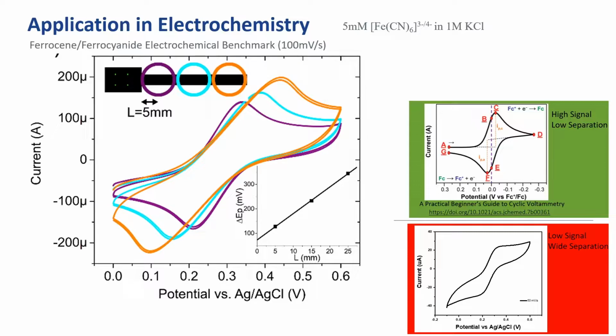To investigate the trade-off between area consumed by the plugs in the active area and the impact of access resistance by entry track length, cyclic voltammograms were carried out at known distances from the contact plugs. The peak separation increased linearly with the increased access resistance. Also evident is the diminishing signal to background with increasing distance. Therefore, if an externally contacted strategy is required, the track should be minimized, if possible, to ensure high-quality electrochemical sensors.